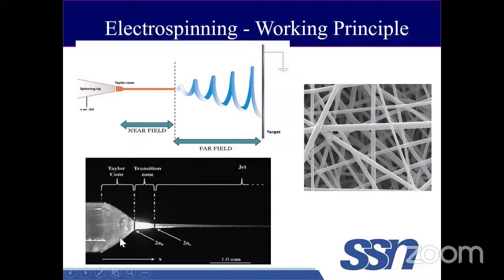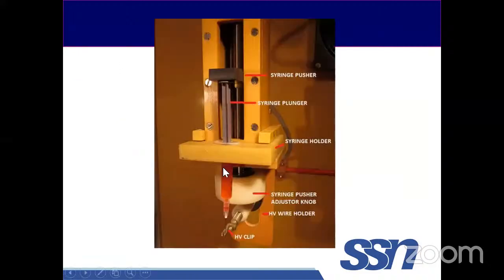This is a typical image of the syringe tip where this polymer solution is coming out, and as we apply the potential, it tends to form the Taylor cone, and there is a transition zone, and at the far field, it starts whipping, right? This is how the instrumentation will look, where we have an infusion pump through which the syringe is connected, which is being pumped at a flow rate, and at the tip, we will be connecting the high voltage. Once the potential that we apply exceeds the surface tension of the polymer solution, the polymer that is coming out from the syringe tip will start whipping. During the process of transmission from the tip to the collector, the solvent will evaporate and the polymer fiber is collected at the collector end.